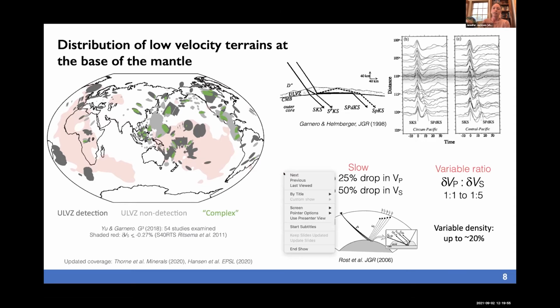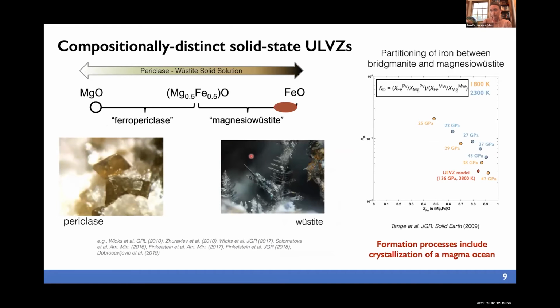And so these observations, especially the strong drop, and the potential for iron-rich phases to crystallize out of a magma ocean, inspired the hypothesis that these ultra-low velocity zones could contain iron-rich MgFeO, or magnesiowüstite. We also looked into partitioning information that has been published so far, and it really shows that under these conditions of the lowermost mantle, iron does prefer to be in the oxide over the silicate, and quite strongly favors the possibility that there could exist an iron-rich MgFeO, and it could be stable.